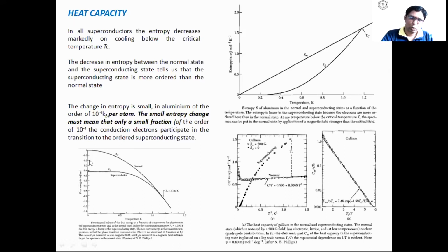This is the free energy. In the normal state, free energy is larger than in the superconducting state. This is the graph plotted for gallium, showing specific heat C against temperature squared. You will see that there is a discontinuity. As the temperature is decreased, at Tc there is a discontinuity in the heat capacity. First it increases and then decreases very fast. So there is a discontinuity in the heat capacity at the critical temperature Tc.